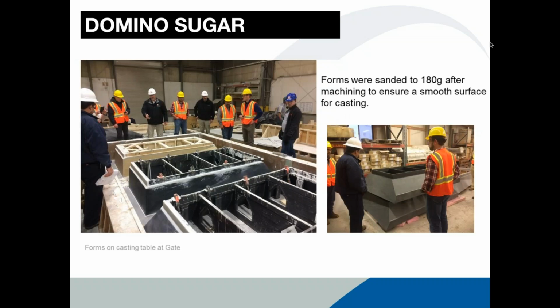Here are some pictures of the forms in the casting beds at Gate's facility. You can see on the left-hand side in the back, there is a wooden form. The reason for that is Gate had identified the forms that were going to be used the most, with a high volume. There were some forms that were cast on 200 times. So there are some very high volume forms in there, and we'll get into that when we talk about the benefits of using an ABS 3D printed form.